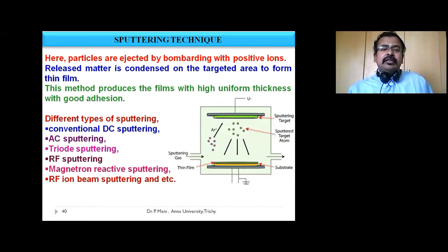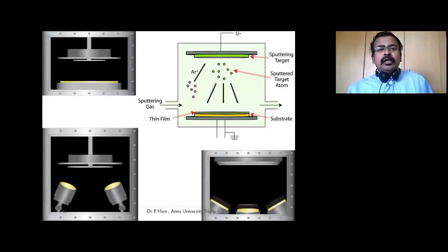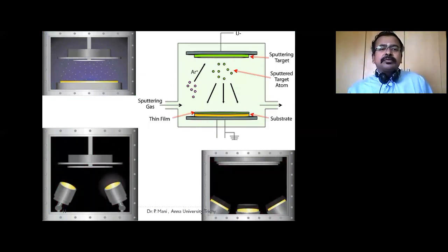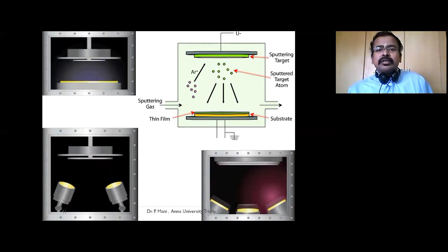Sputtering technique: here the particles are ejected by bombarding with positive ions. The released matter is condensed on the targeted area to form a thin film. This method produces films of highly uniform thickness with good adhesion. We know different types of sputtering: conventional DC sputtering, AC sputtering, triode sputtering, RF sputtering, magnetron reactive sputtering, RF ion beam sputtering, and so on. Here we are seeing different types of sputtering, single element and compound.